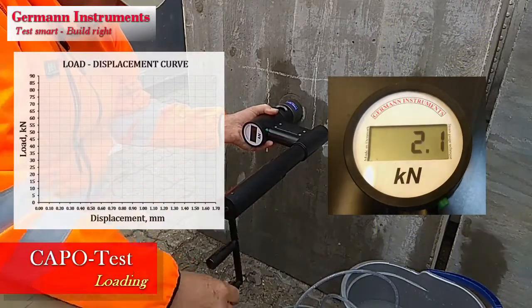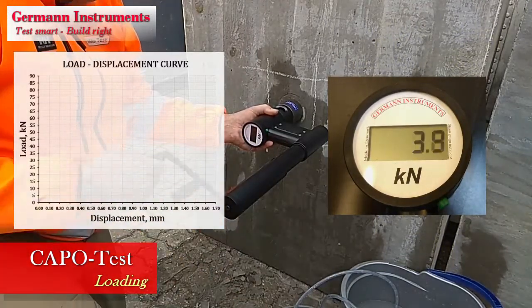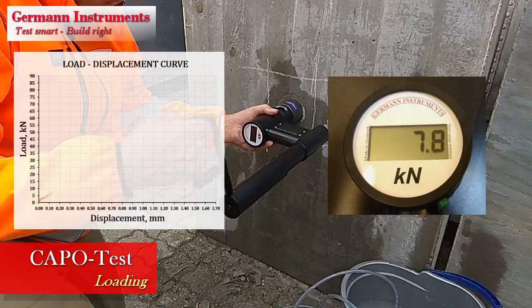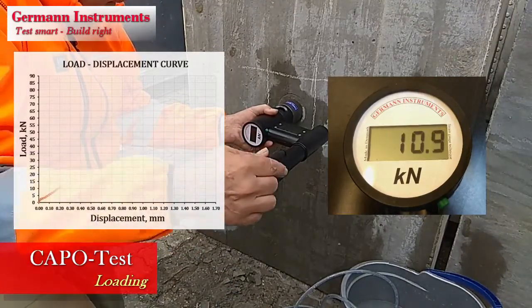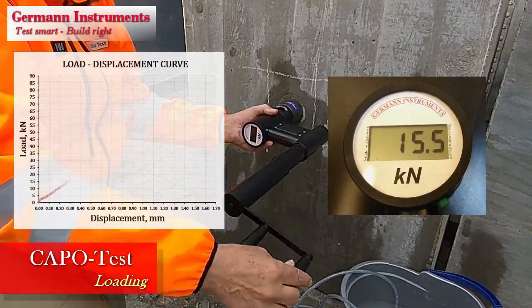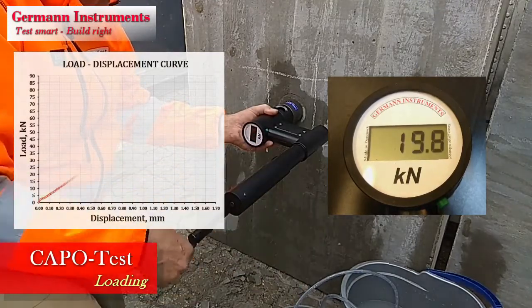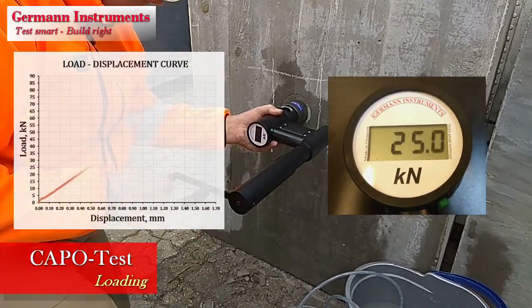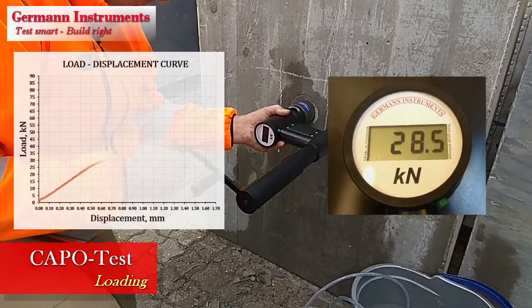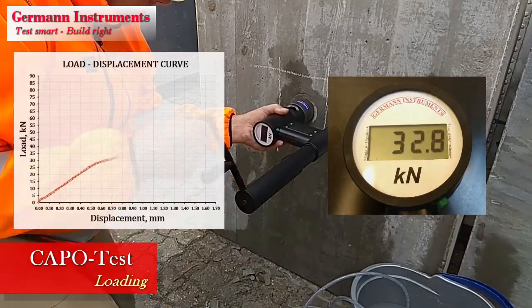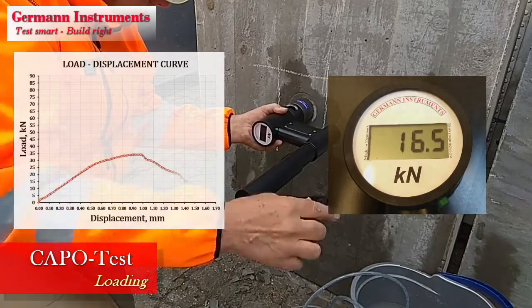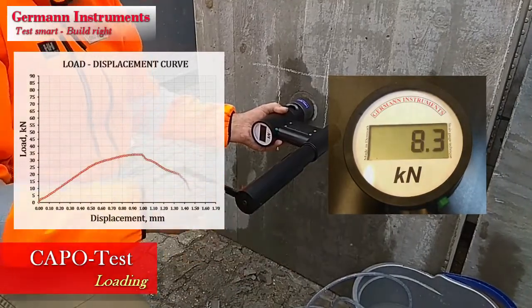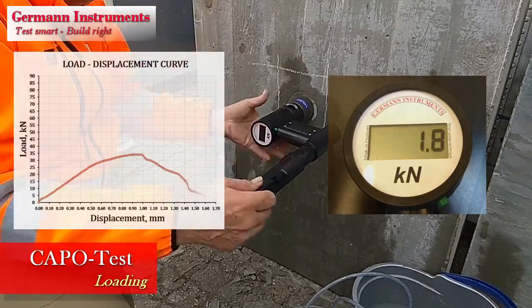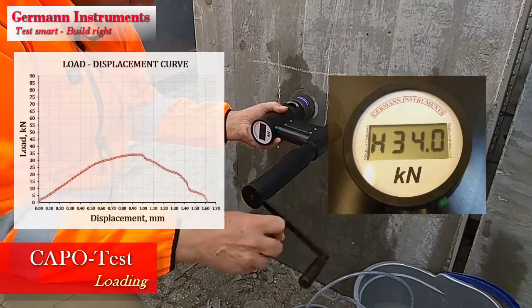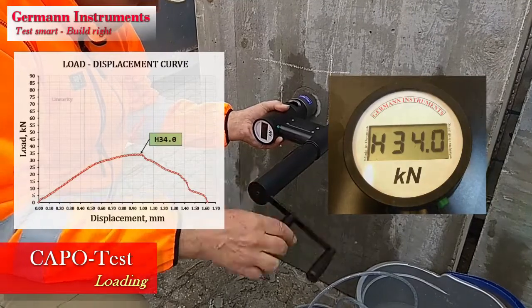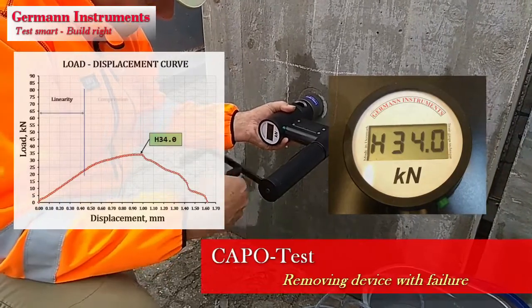Turn the loading telescope handle slowly clockwise with a uniform speed. One pull-out test has to last minimum 15 seconds. The rate of loading should be about 2 to 3 seconds per turn of the handle, so go easy, and hold the instrument's pistol shaft with the other hand. Keep on loading until the maximum pull force has been reached, then turn the handle quickly counter-clockwise to release the pull-out cone. The peak load will be shown on the gauge with an H in front. In this case the peak load is 34.0 kN.